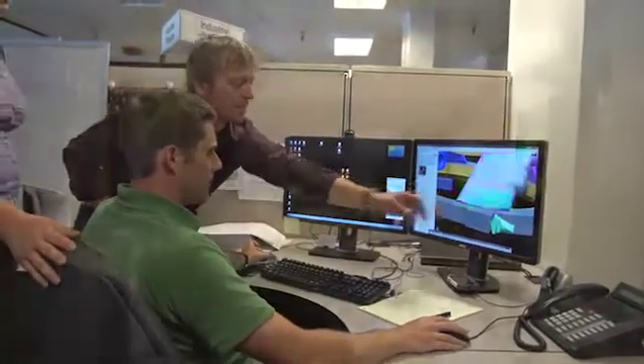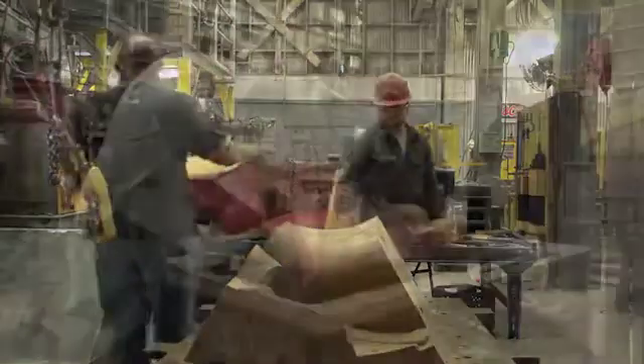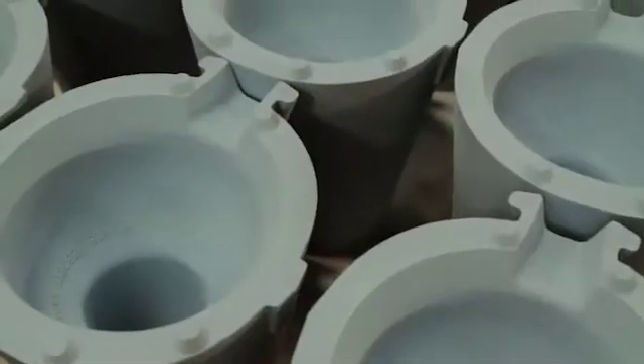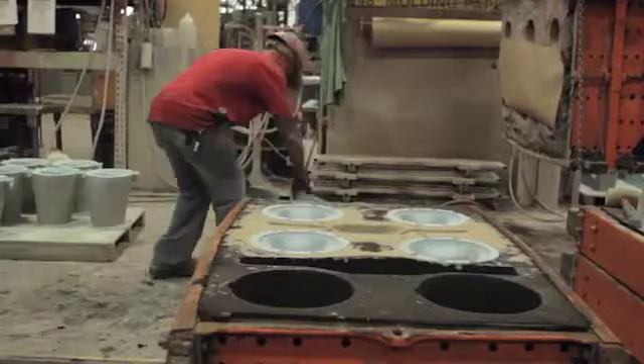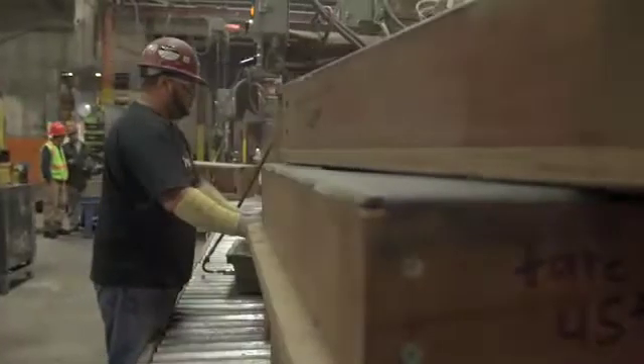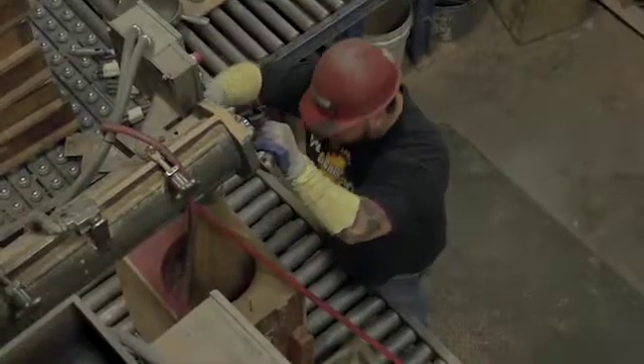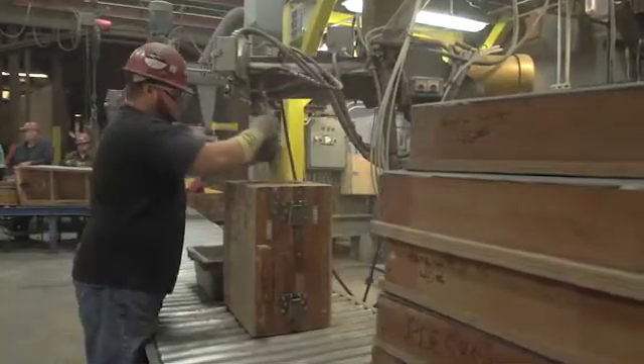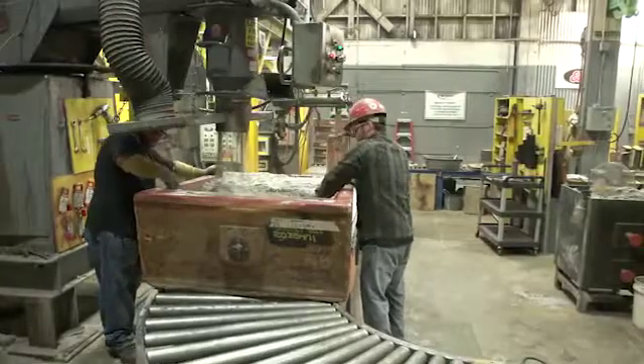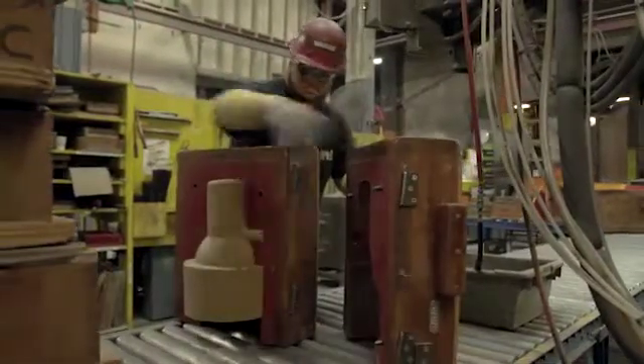The manufacturing process starts by building the 14 cores needed for the cutterhead. Cores form the hub, the cutter arms, the weld land for the cutter arms, and cutter arm adapter sockets. The core creates the desired shape of the cutterhead elements and is made by packing coated sand into the forms. A catalyst is added to the sand mixture which makes the sand harden to a brick-like texture after curing. Cores are also made by using a machine to blow the sand into the core or by using a combination of both processes. A core is used just one time, but the sand is recycled for repeated use.